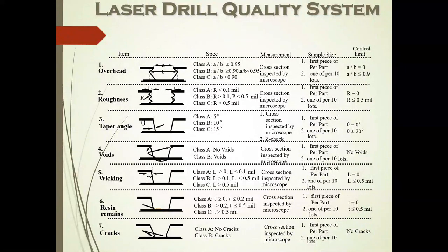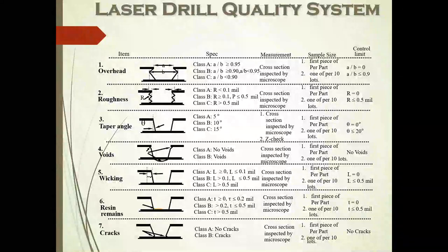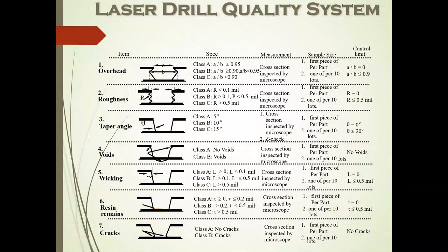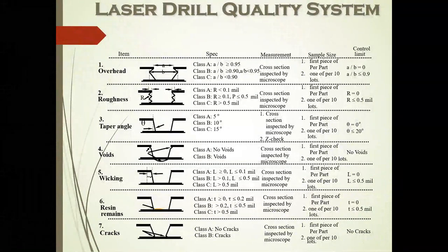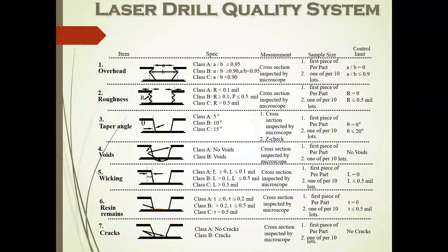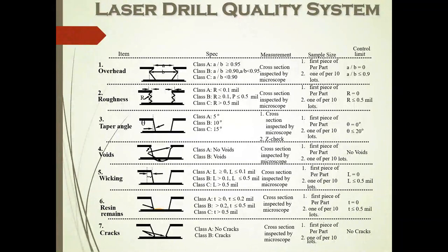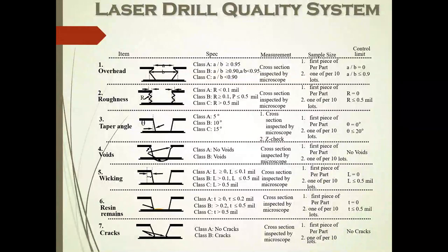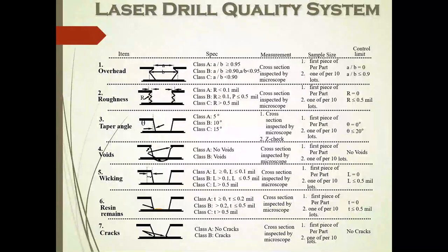You have to cross-section and look at your blind vias in these seven areas. The specs for A, B, and C show what you measure, what the control limits are, and the sample size. Because these things are so small that you really can't use optical inspection to determine what they look like, you need to have worked with the fabricator closely to understand that they have optimized your particular stack of material selection and design rules.